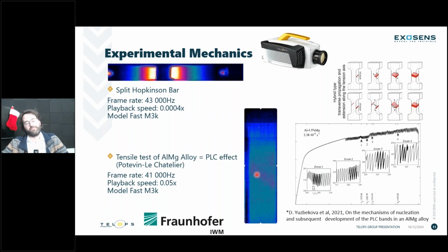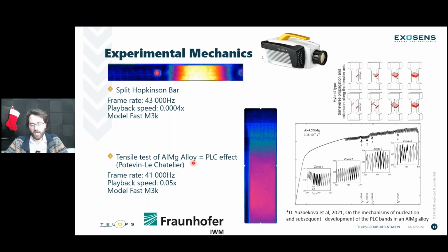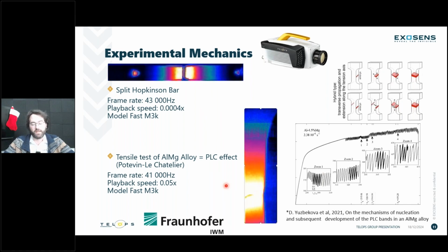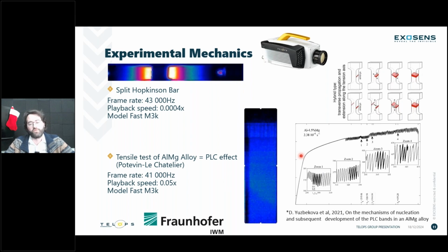Otherwise, at the bottom here, it's a really fascinating material behavior. That's what happens with a magnesium alloy, in this case, the aluminum magnesium alloy. And we see very well what's called the PLC effect, or the Portevin-Le Chatelier effect. It's a phenomenon that happens in a tensile stress test, where you have those dislocations happening in the alloy, but in a specific angle depending on the alloy itself. In the stress test, if you're familiar with this kind of testing, you might be familiar with this PLC effect that creates a peculiar effect in the stress strain curve that we have here.